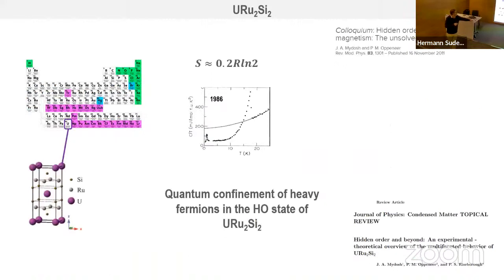So we set up on this problem, and we started on uranium ruthenium two silicon. I will speak more about this material later. Just let me show you that, well, it's a heavy fermion, okay? And then it enters here a peculiar transition. We are going to work here at low temperatures inside this transition, but I'm going to show this transition a little bit later. It's a very peculiar transition because it carries a huge entropy, but no one knows what is ordering. Of course some electron property is ordering, but no one knows what it is. It is not magnetism, and that's essentially what we know.